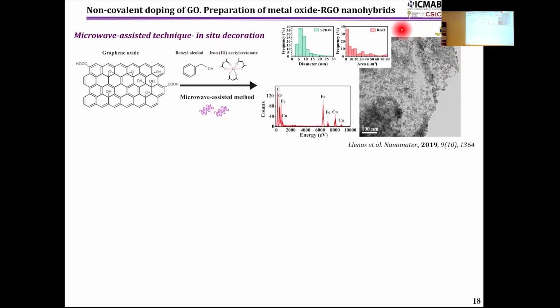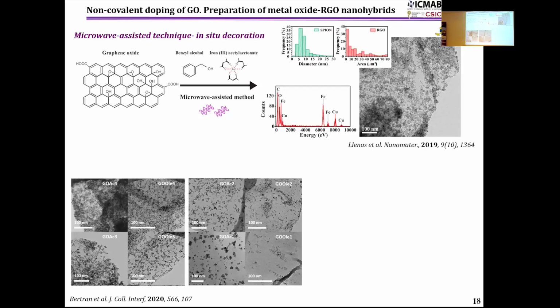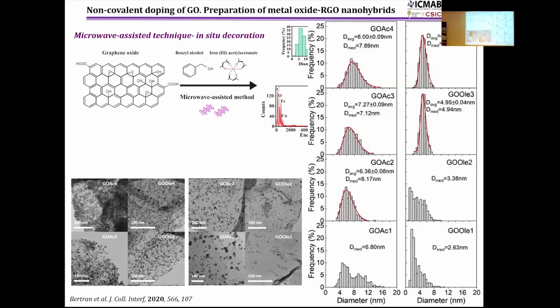And one thing that we considered is that this protocol, which is an in situ protocol based on the decomposition of a salt, usually doesn't allow the control of the loading of the nanoparticles onto the graphene oxide. So we tuned this loading by changing the organic group attached to the precursor. By using oleates and acetates, we were able to change this loading and tune the separation of the particles, which usually agglomerate onto the graphene oxide layer, but also tune the amount of particles which are attached on top of the material.